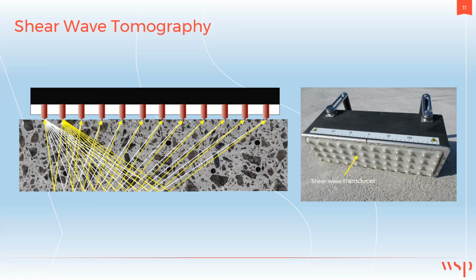Another related stress wave method is referred to as shear wave tomography. As opposed to a P wave or compression wave, which is essentially a wave in and out of the specimen, a shear wave is transverse to the test surface of the specimen, but propagates through the element in the same way, in that it reflects down to a boundary where it is reflected or refracted.